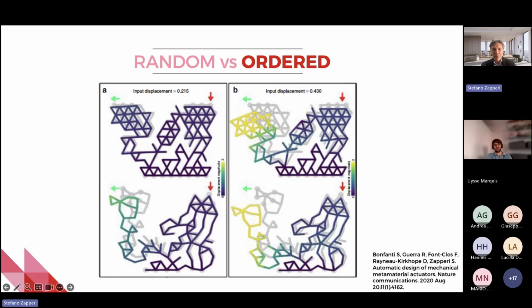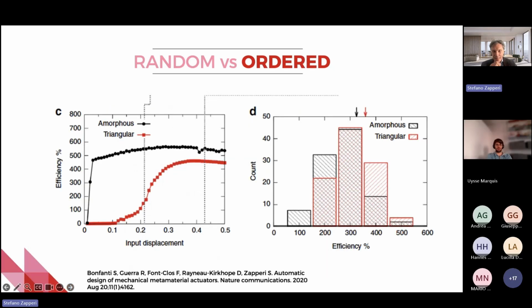We can also start from random lattices, like instead of starting from a triangular lattice, we can start from a random lattice, and okay, we can improve somehow the results. Here is again the same actuator as before, and typically the efficiency is a bit better when you start from an amorphous type of structure rather than a triangular lattice. Okay, you have more configurations when you are amorphous. In this case, it's not always so. Sometimes the ordered lattice is better. Like in the auxetic, you cannot beat the perfect bow tie lattice.